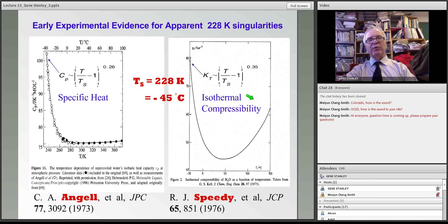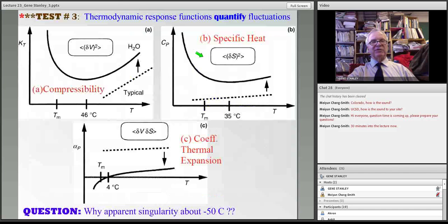Like most liquids, the compressibility decreases on cooling, but below 46 Celsius, it actually increases again by about 40 or 50%. Furthermore, these increases can be fit by power laws, where there appears to be a singularity temperature, Ts for singularity, at a temperature that's below the homogeneous nucleation. It's about 228. And homogeneous nucleation we saw was at -38 Celsius, so that's about 235. So you can't get down to the critical point because the line of homogeneous nucleation forms a fence that you cannot go over, but the fact that data fit a power law means there has to be a reason. And if there were a critical point, this would be a sufficient reason.